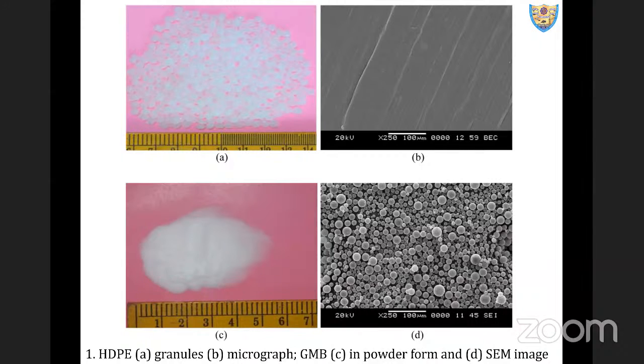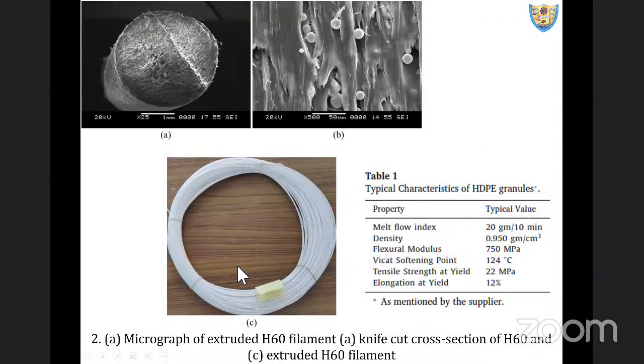We chose the suitable barrel and die temperature to convert solid pellets into a semi-solid state and extrude it from the die without any material blockage and breakage. As I mentioned earlier, the filament size depends on the extrusion rate, that is the screw speed, and takeoff speed. HDPE and GMB pellets are fed to the screw and we draw the filament of 2.85 plus minus 50 microns to be fed to a 3D printer. Now, all these parameters are chosen by considering HDP melting temperature, uniform and homogeneous mixing of GMB in HDP without breakage, the rheological behavior of blends, and also the presence of porosity, if any, during extrusion.